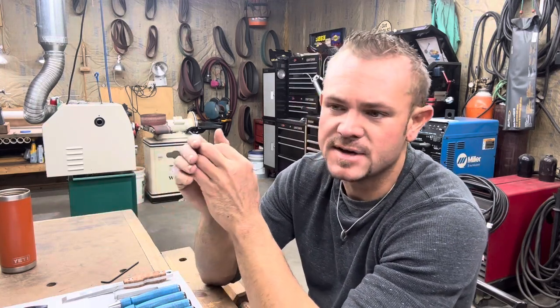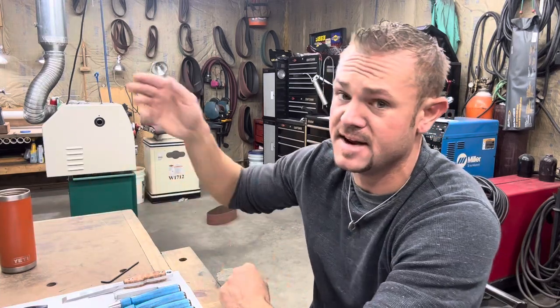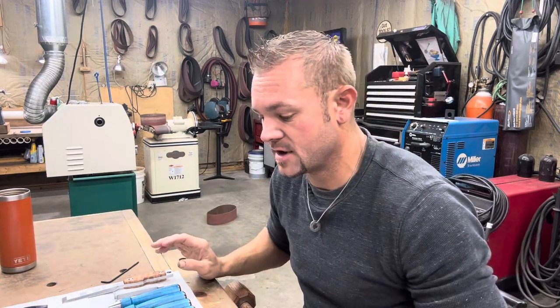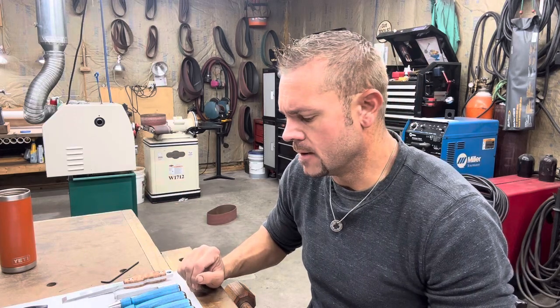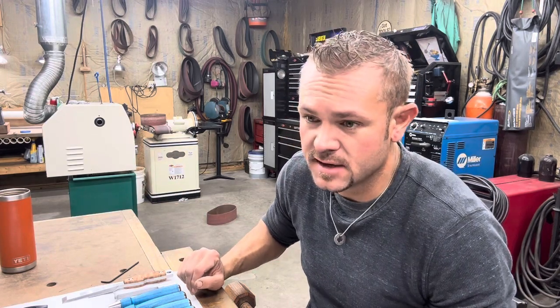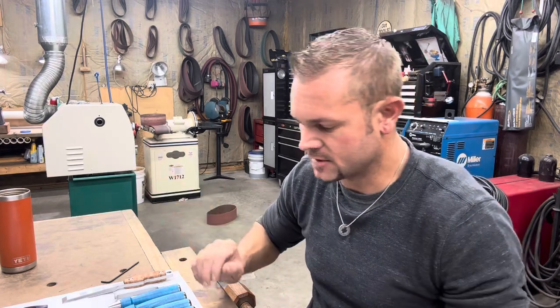And you shouldn't have retained austenite in A2 or O1. You shouldn't have a massive amount of retained austenite to the point where when you employ cryogenics, you're getting a conversion. There shouldn't be anything left to convert to martensite during the cryogenic process. And if there is, you messed up your heat treatment. Whoever's, because most of these companies contract it out, whoever's doing your heat treatment for you could do much better. So 9 times out of 10, it's marketing. Cryo, we're better. That's the whole thing.